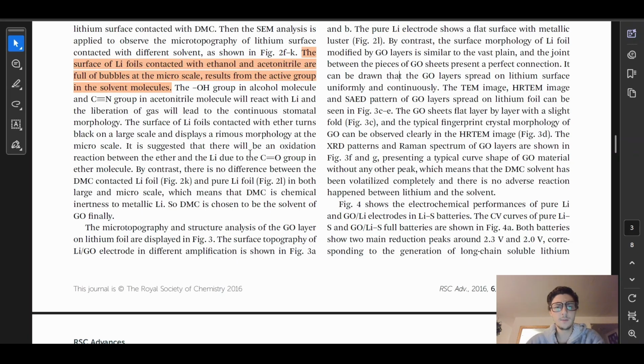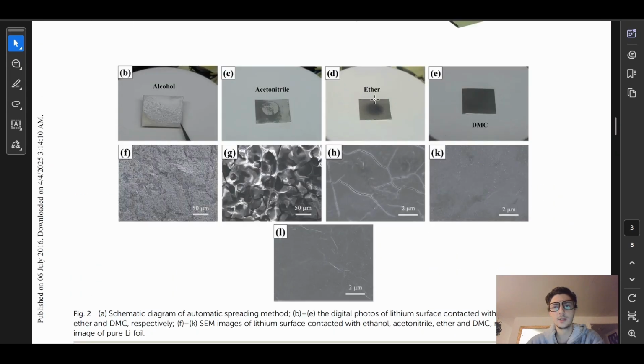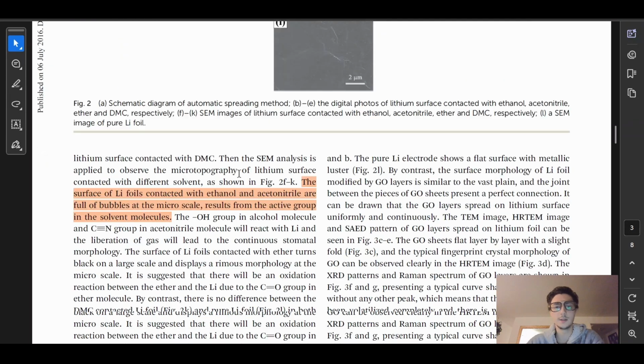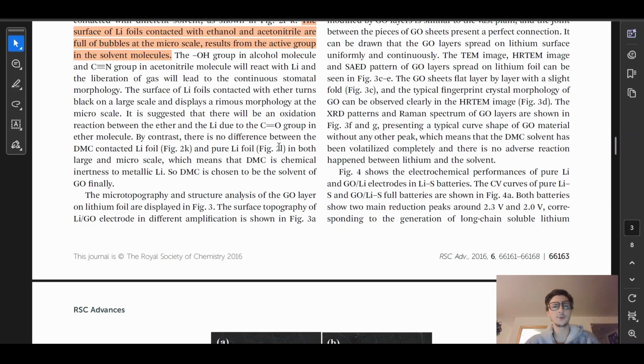It is suggested that there will be an oxidation reaction between the ether and the lithium due to the C double bond O group in the ether molecule. So this is the ether here. So they're explaining why all these things happen with the lithium here. And I'm assuming they're going to get to the DMC here. By contrast, there is no difference between the DMC contacted lithium foil, figure 2K, and pure lithium foil, figure 2L, I'm assuming, in both large and micro scale, which means that the DMC is chemically inert to metallic lithium. Interesting. So DMC is chosen to be the solvent of GO finally.